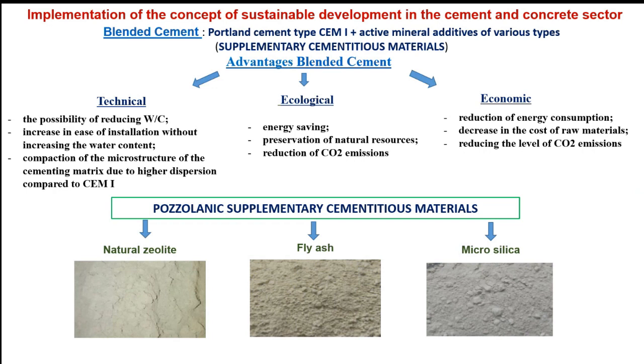The problem of energy efficiency and reducing CO2 emission in building production is largely determined by a set of more ecological ways to replace a part of Portland cement clinker with supplementary cementitious materials. Due to the rational selection of cementitious materials in the production of low-carbon cement, technical, ecological, and economic effects are achieved. Pozzolanic supplementary materials such as natural zeolite, fly ash, and microsilica were used.